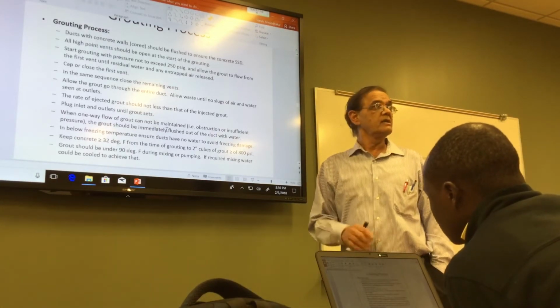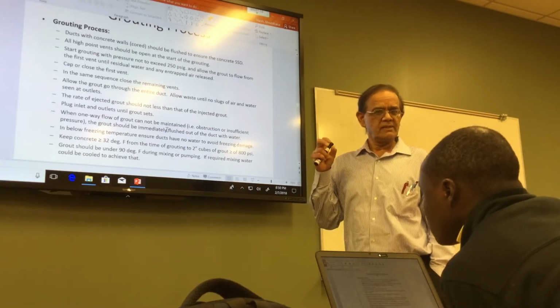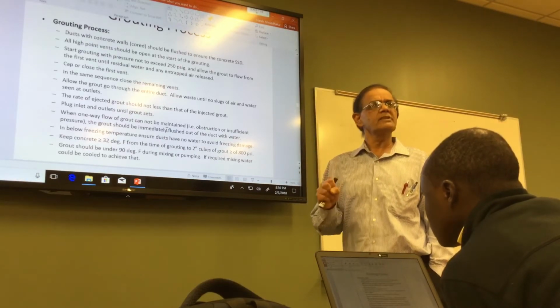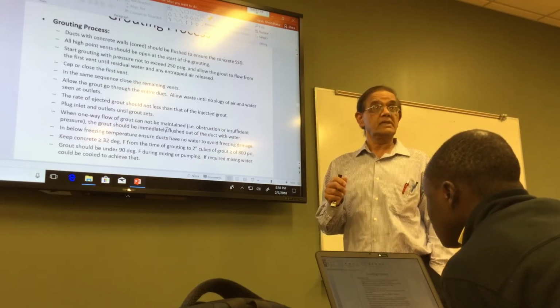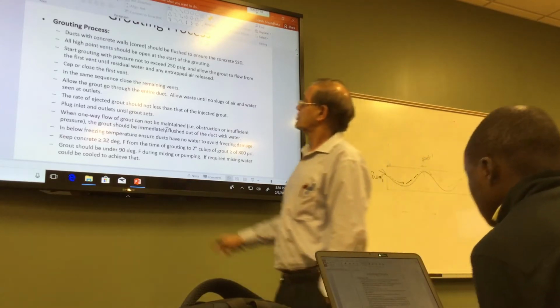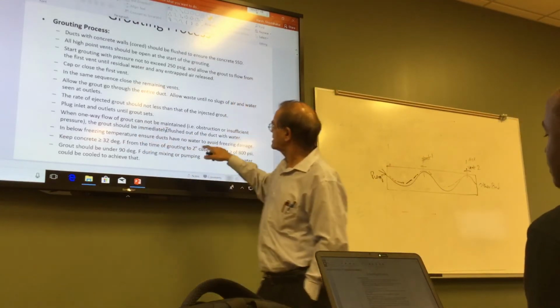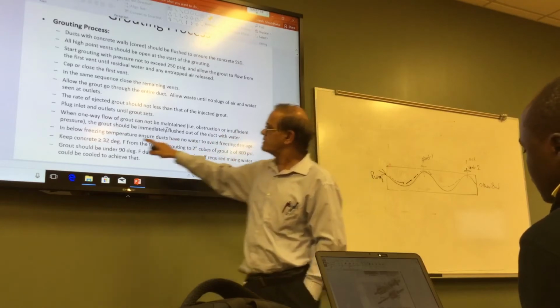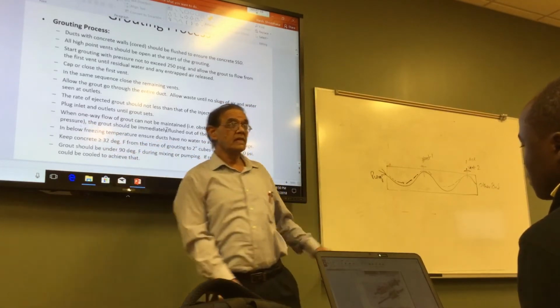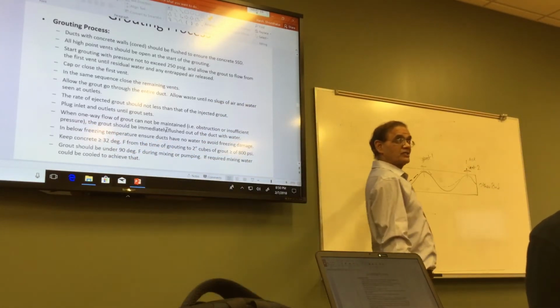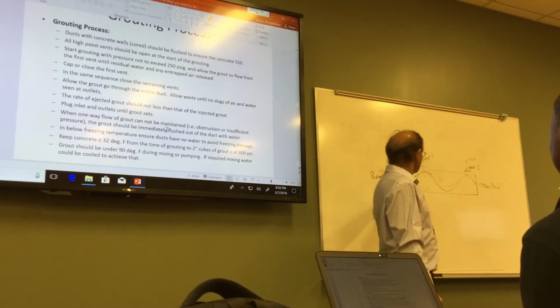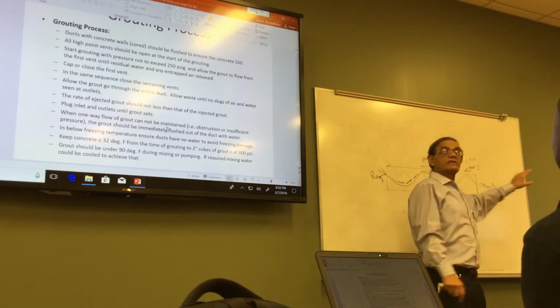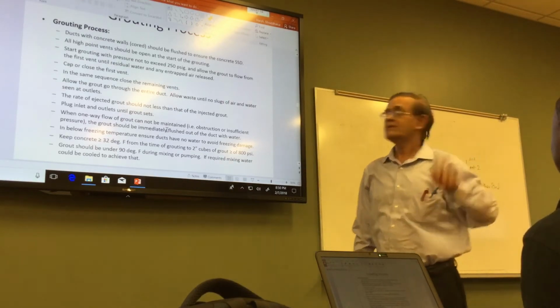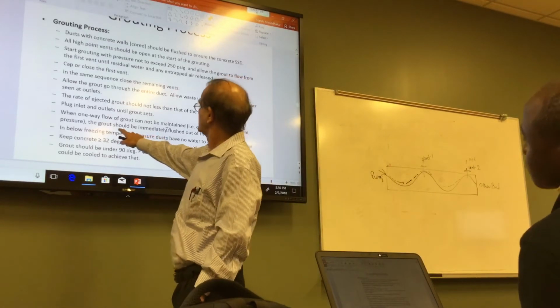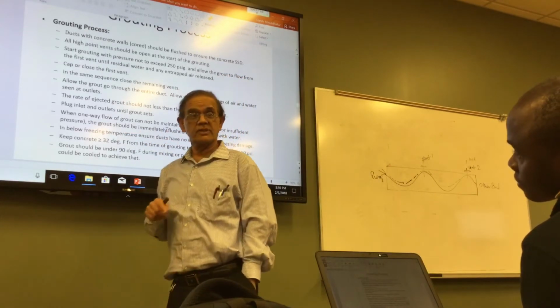It's not moving. There is an obstruction. The tendon has been crimped because of damage, right? So it's not moving. So when one-way flow of grout cannot be maintained, there is an obstruction or insufficient pressure, because for hydraulic flow, you need some pressure, right? If there is not sufficient pressure, then it won't go over this because of the hydraulic gradient, right? So the grout should be immediately flushed out because you have a problem.